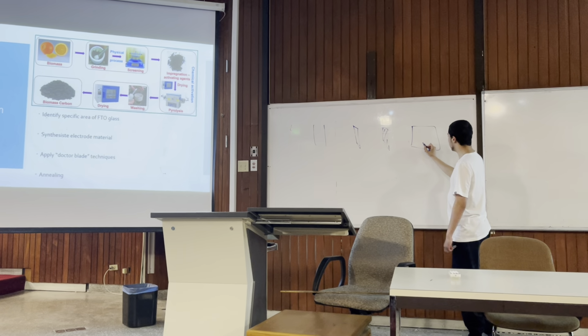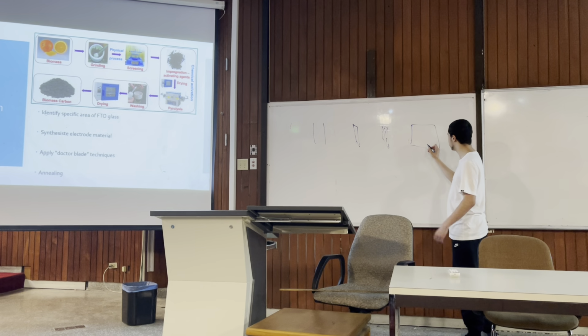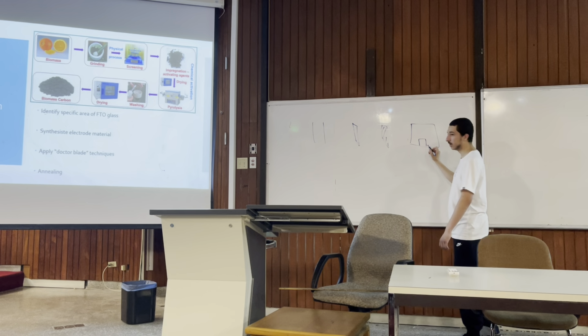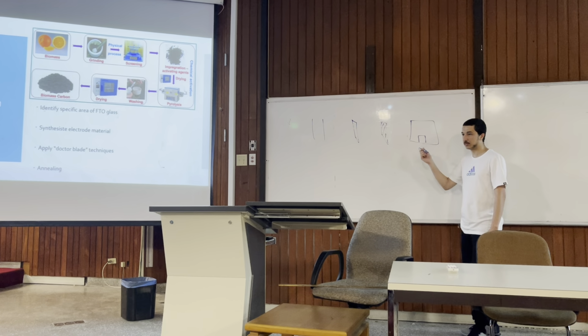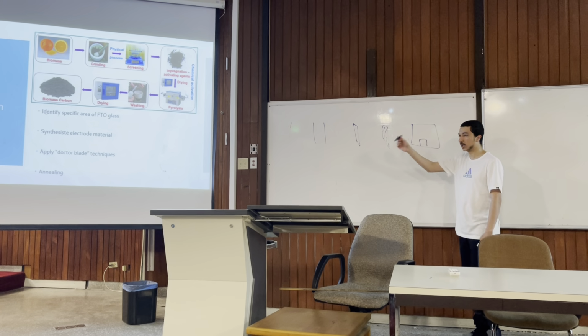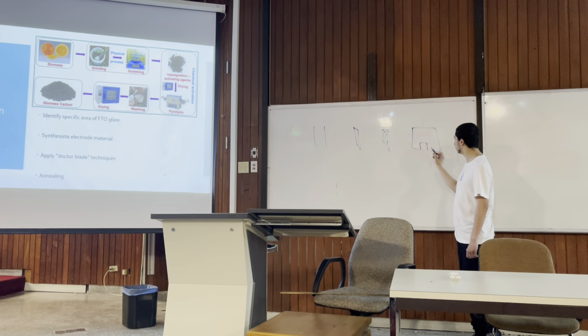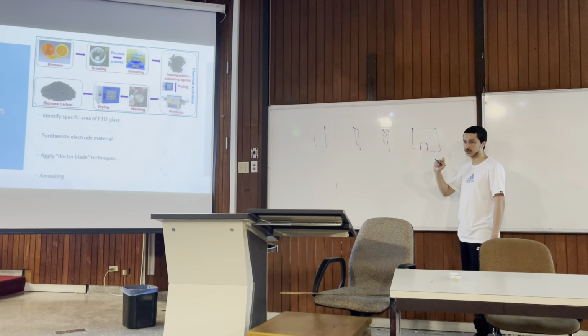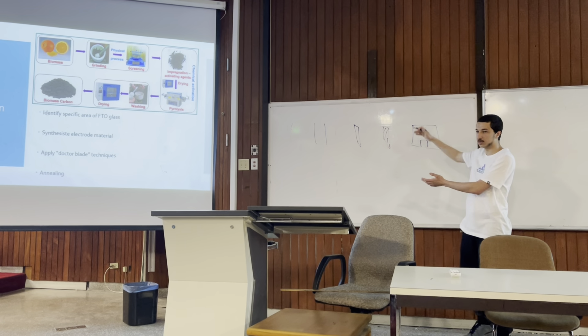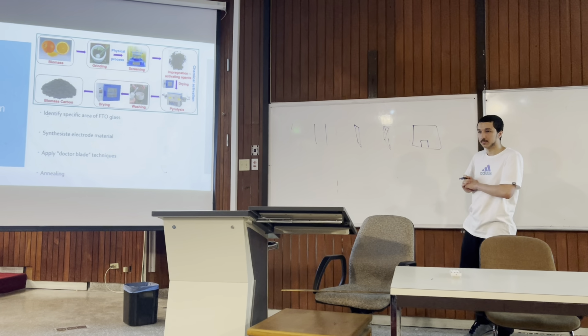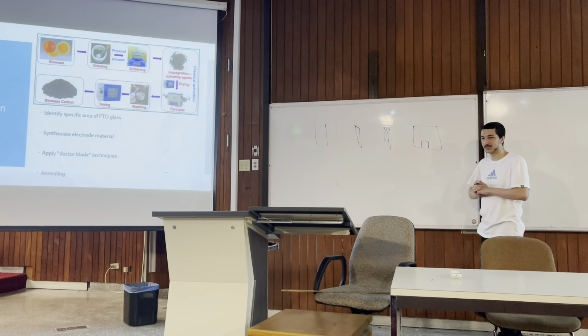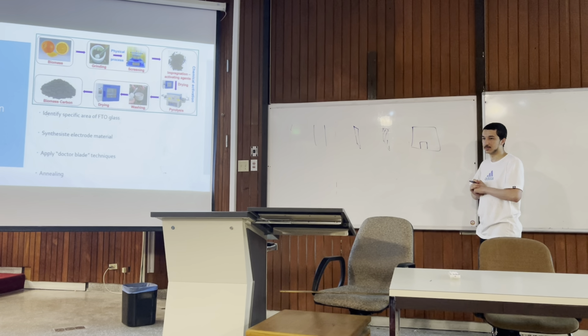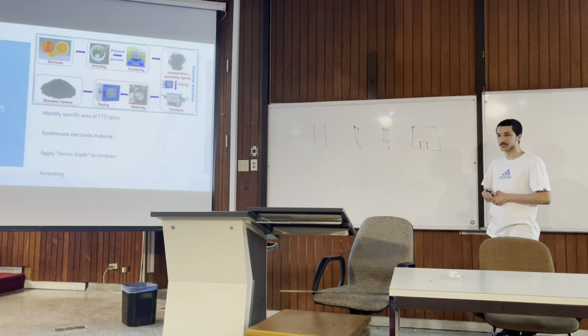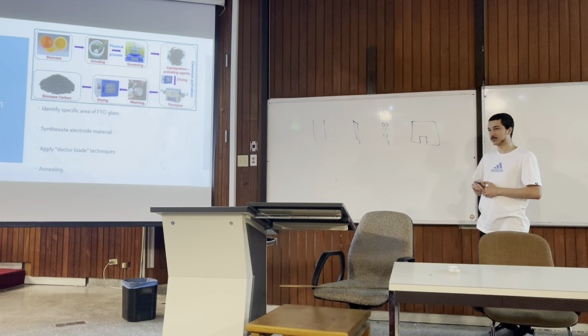What we do is we identify a specific area, usually 1 centimeter by 1 centimeter, and this is the area where we put carbon or TiO2 or any other material. So this acts as our plate for the supercapacitor, rather than having a very large supercapacitor. The unit is areal capacitance: farad per centimeter squared or farad per meter squared.